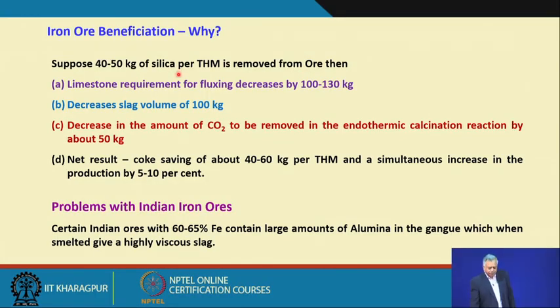So that is why the number is, suppose 40 to 50 kg of silica per ton of hot metal is removed from ore by mineral processing, then the limestone requirement for fluxing decreases by 100 to 130 kg. So, you are not only removing 50 kg of silica, you are also reducing the consumption of limestone by 100 to 130 kg per ton of hot metal. And it decreases the slag volume by 100 kg. Decrease in the amount of CO2 to be removed in the endothermic calcination reaction by about 50 kg.